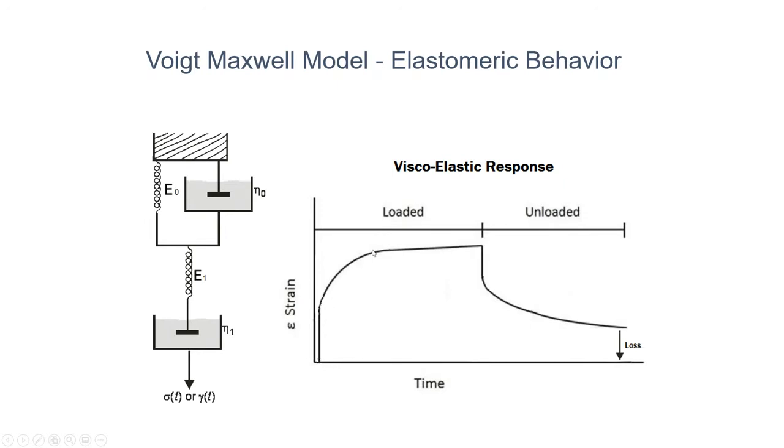material. What we find is the springs. If rubber were a perfect spring, which it is not by a long ways in its raw form, then we would simply load and unload and it would return to the same spot. But when we unload a material, there's always some component of loss. This is that double prime data that we see.